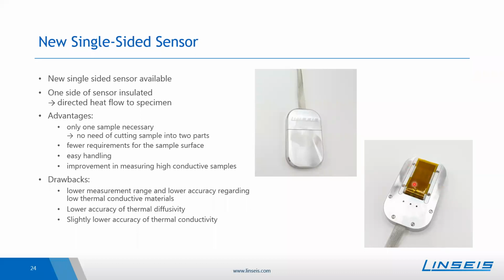As you can see, here is the design of the QSS sensor, more or less the QSS sensor within this single-sided setup. The advantage of the single-sided sensor is, of course, that you just need one sample piece. Typically one cuts a sample piece into two halves and sandwiches the sensor between them. With this sensor, you do not need to damage or destroy your sample piece to realize a measurement.